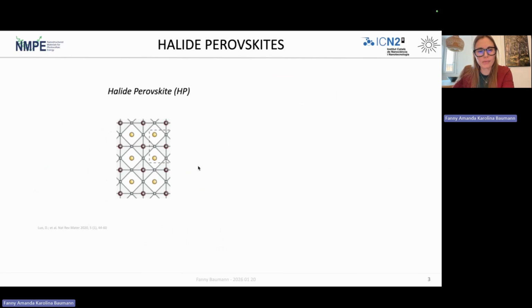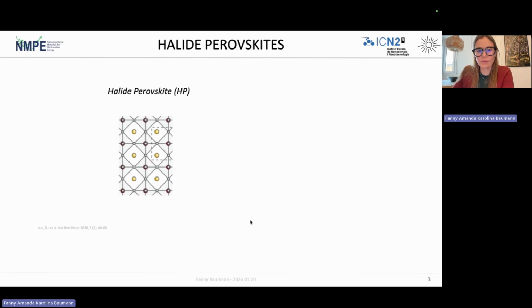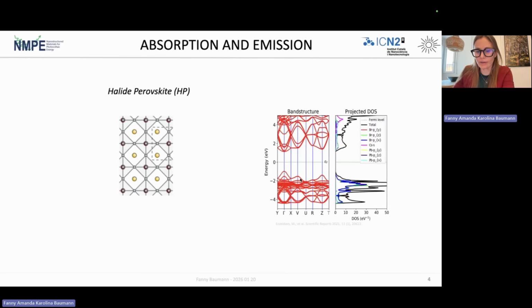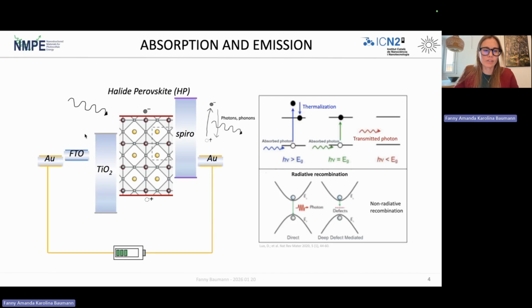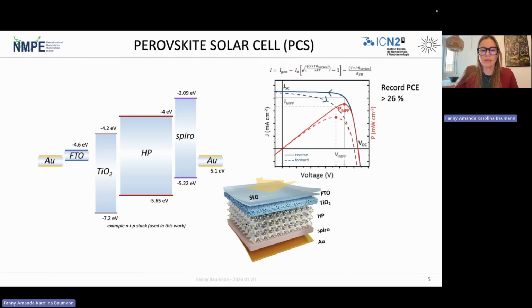When we want to use halide perovskites in a solar cell, we utilize that they have a direct, rather adequate band gap with large charge separation and long carrier lifetimes. And thanks to this, we can just sandwich the perovskite layer between adequate selective layers to extract electrons and holes at either side of the device. And when the device is illuminated, we can obtain an internal electric field and electricity.